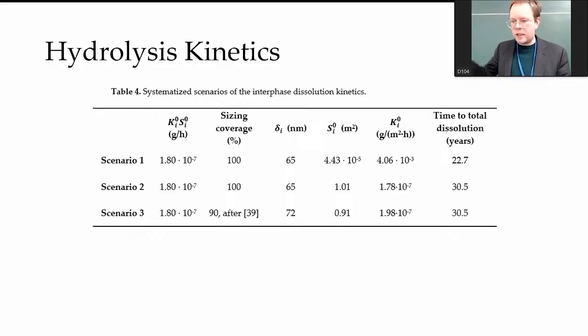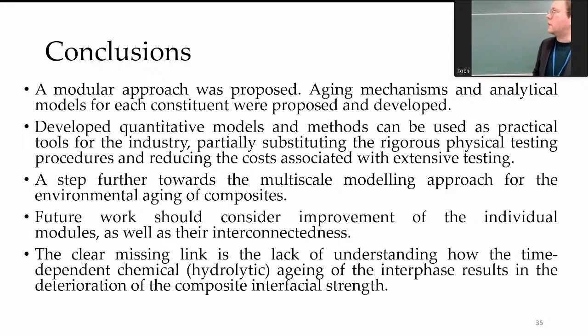And interestingly, this kinetic constant that we estimated for the degradation of the interface is very similar to the degradation kinetic constant of glass fiber, which makes sense because it's silica or silane bonds that connect matrix and fiber. So to conclude, basically, I would say that we have proposed this modular approach, and I apologize, it's a lot of information that we tried to put together. It's many years of things that we tried to do.